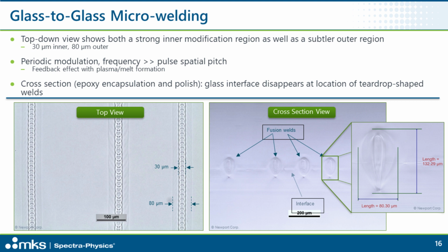Our first result to show is glass-to-glass micro-welding. These are 2 glass plates, about 1 millimeter thick, contacted optically, so there's no air gap in between. And we see a top-down microscope view showing a very clearly modified region, which we hope is where the glass is fused together. The central stronger modification is about 30 microns wide, and we have a larger, more gentle modification of about 80 microns wide.